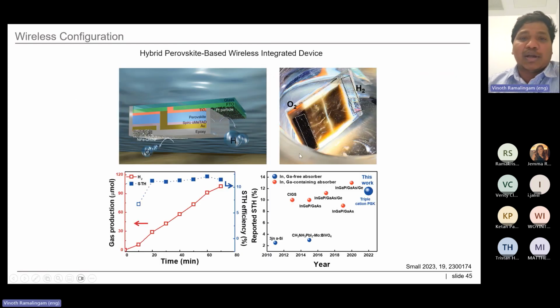So this is the wireless configuration. As I mentioned earlier, you don't have any wires here. This is from recent literature, where they used a hybrid perovskite-based wireless integrated device. These are the devices you see. For example, this is a photoanode and this is a photocathode. These two devices are separated, whereas their catalysts are connected to the photoelectrode. In that case, you just shine light, and hydrogen comes out from one side, that means from the photocathode side, and the oxygen comes from the photoanode side.